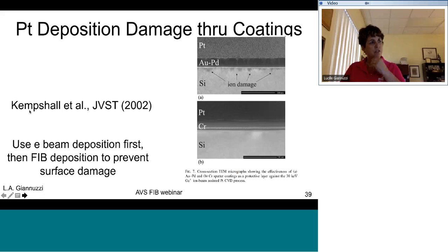The other thing that you can do is protect your top layers through a coating, through a sputter coating. But you have to be careful of sputter coating, because if you don't use a continuous sputter coating, you can get ion beam platinum damage through the coating. So this is silicon. This was deposited with gold palladium. Gold palladium goes down as islands, and then this was FIB deposited with ion beam platinum. And you see that you can actually get damage of the 30 kV ion platinum through the islands. So if you're going to put coating on something, make sure it's a continuous coating. Okay?